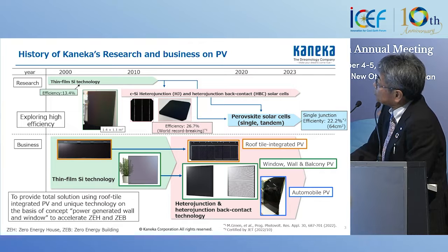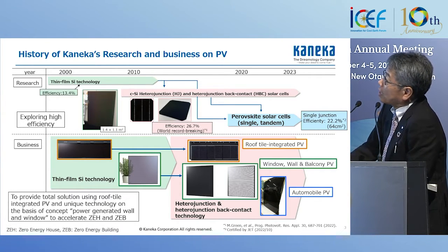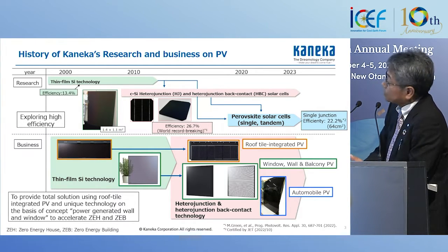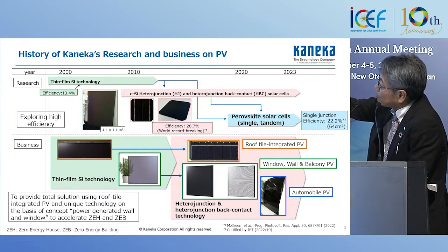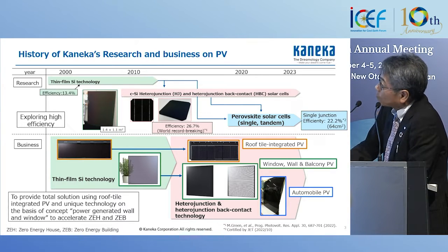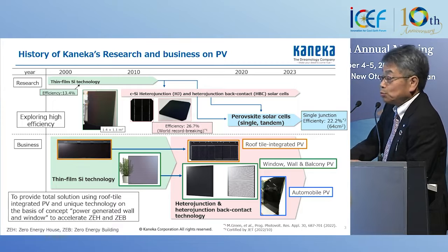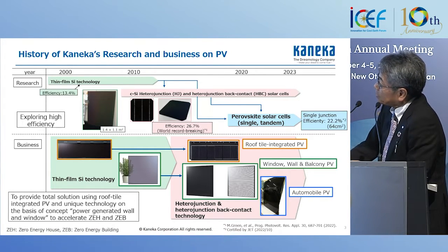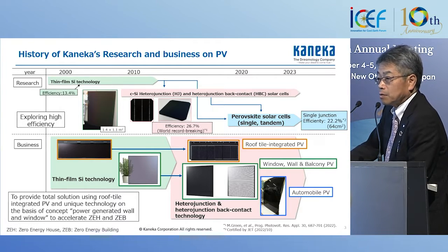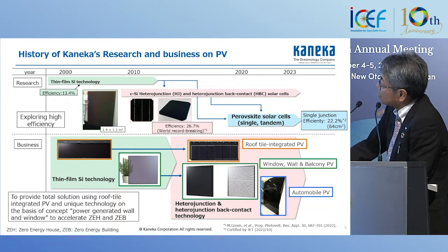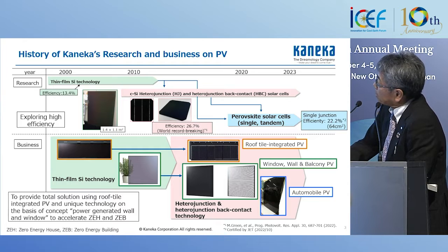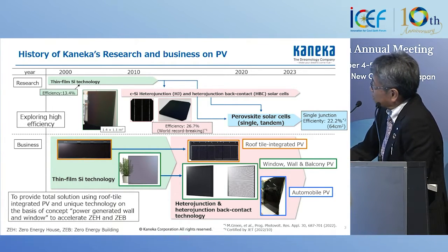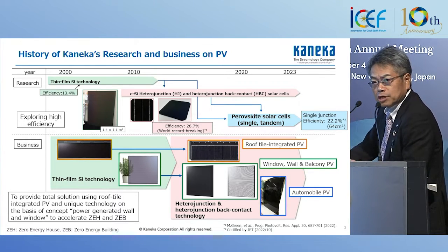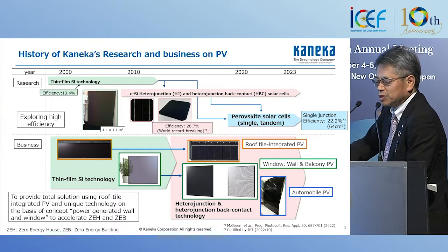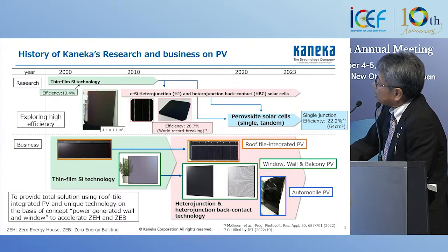This is our history of research and business. We had been manufacturing thin film silicon. The perovskite is anyway a thin film device, thin film module. At that time, we made it 1.4 by 1.1 meter, and then switched to silicon. The main reason is that the efficiency of thin film silicon is not good enough. And then we showed a world record efficiency of 26.7% for our silicon cell. Over 5 years we were the holder, but unfortunately, almost 1 year ago, it was replaced by 26.8%, only a 0.1% increase, by a Chinese company. And we also have a world record for the module, but unfortunately, 3 months ago, it was also replaced by US SunPower.